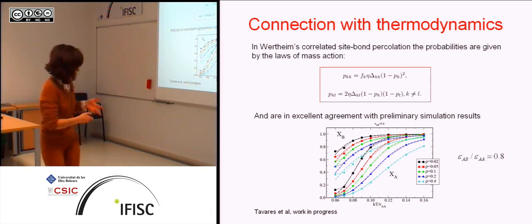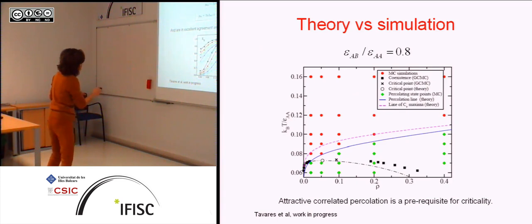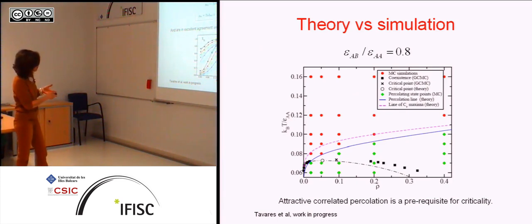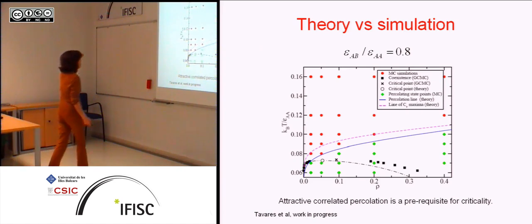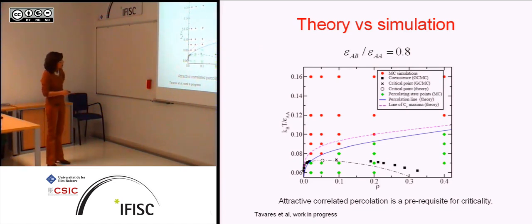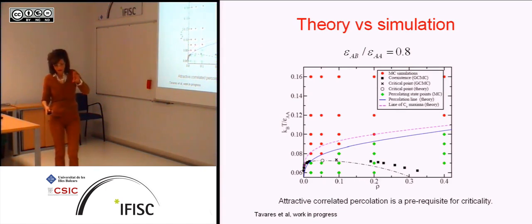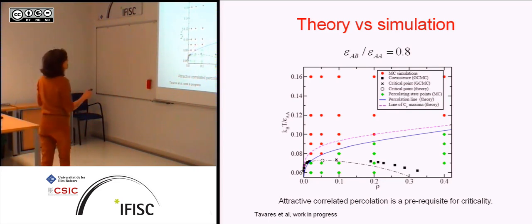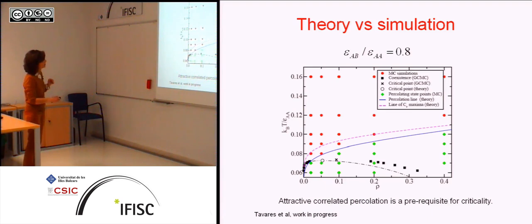through these routes. And so these are some simulations for the association. So in these limit low densities, we're doing quite well. And this is a summary of the results. So this is temperature, this is density, this is a system that has AA interactions, two sides array, AA interactions, no BB. And then we have a cross interaction, which is about the size but smaller than the AA interactions. And these are the simulation points. This is temperature, as I said, this is density, and this is the phase diagram. This is the simulation phase diagram, squares, this is the theoretical one, these are the critical points.